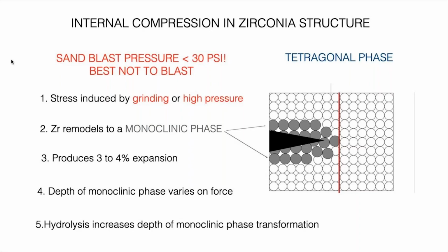Well, let's go to here. So what happens if you press too much on zirconia? This is the most problematic situation when you have 3Y zirconia, where that stuff pushes back. It's almost like if a big bad wolf is at your front door and all your friends, once they hear the door starting to cave in, they gather around and push back to keep the wolf from coming in. So the crack is stopped by a phase transformation. And so that produces 3 to 4% expansion. And that's what keeps zirconia so strong. It changes from a tetragonal phase to a monoclinic phase.